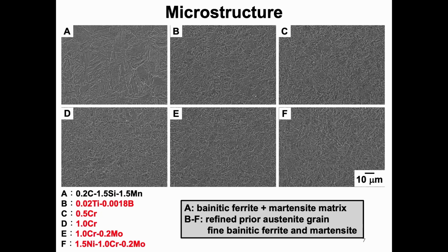This figure shows the microstructure of TBM steels. The microstructure of steel A consisted of a bainitic ferrite and martensite matrix with a grain diameter of approximately 20 micrometer and retained austenite. On the other hand, in the microalloyed TBM steels, the fine bainitic ferrite and martensite matrix were observed. Although we could not distinguish the bainitic ferrite and martensite, the amount of martensite increased by the addition of alloying element.